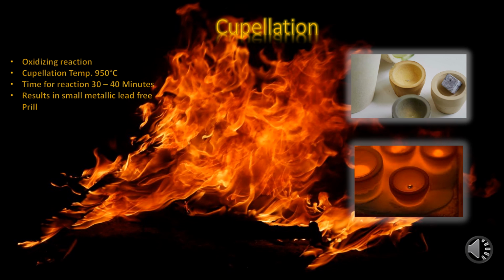Some of the lead oxide and other gases are removed due to their volatilization characteristics. This leaves a more purified button which will contain the gold, silver, and platinum group metals if they are present. The silver will be present and alloyed with the gold. The platinum group metals may or may not be present, and if so, in small, minute quantities. This small lead-free bead is further referred to as a prill or a dore bead.